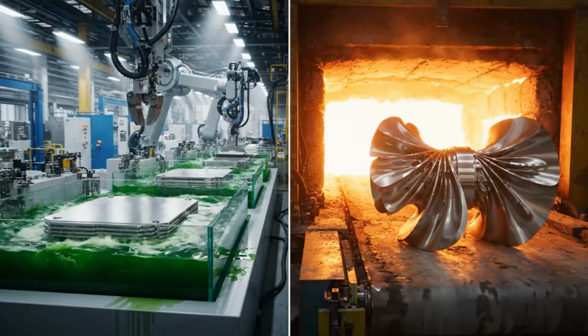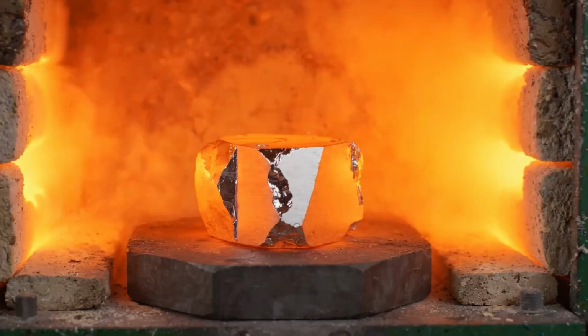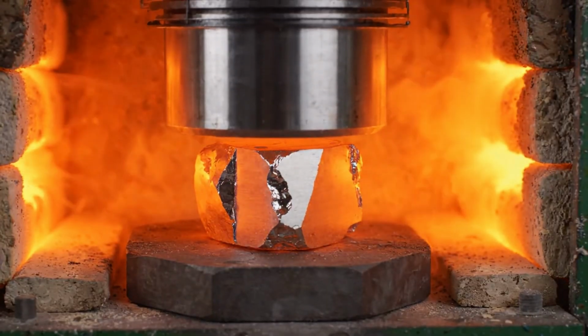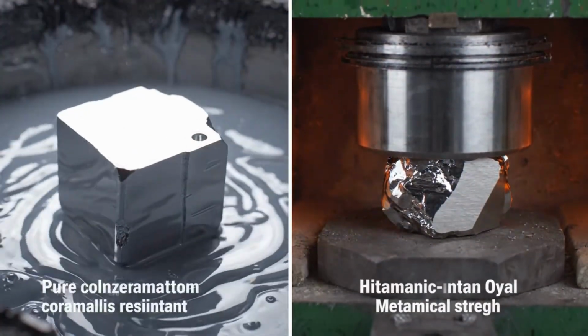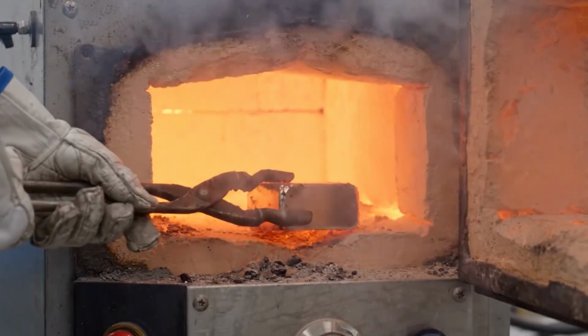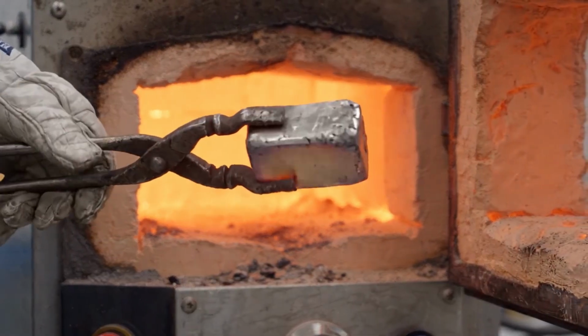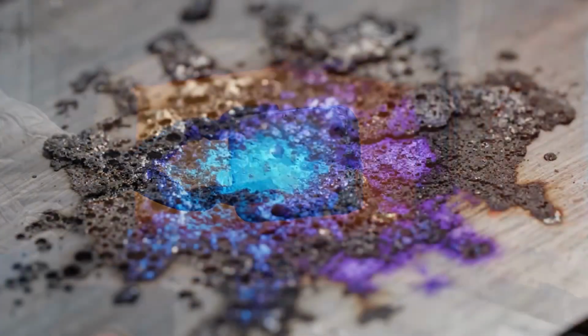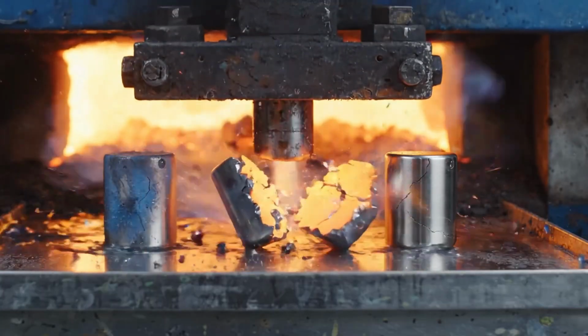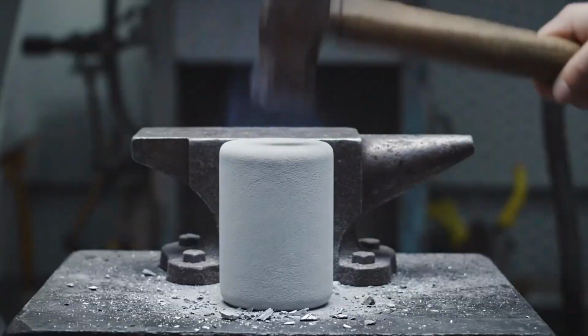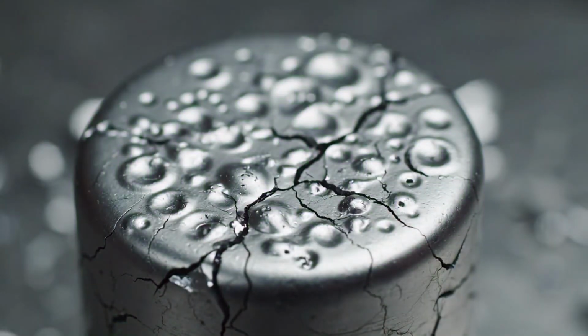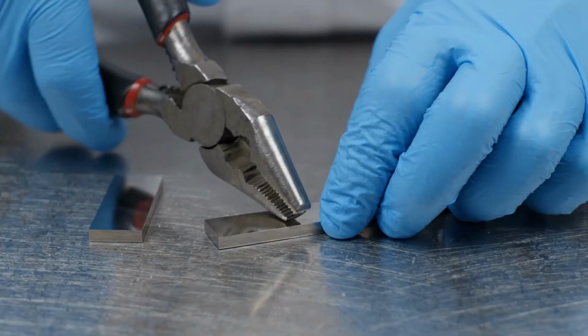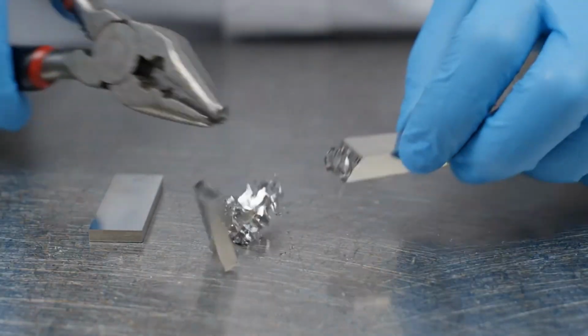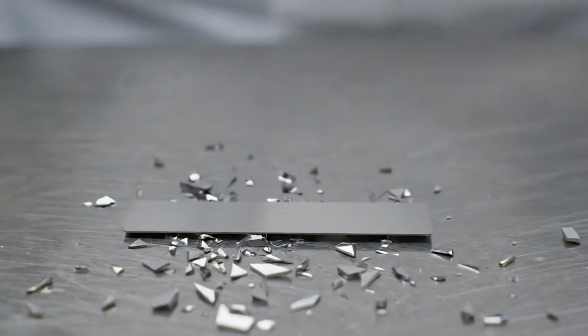This part of the process reveals another characteristic of titanium. It is strong, but delicate during manufacturing. At high temperatures, it readily absorbs gases. Oxygen can overharden it and reduce its ductility. Nitrogen can make it brittle. Hydrogen can cause internal problems. For this reason, operations are carried out under vacuum, argon, or controlled atmospheres. Industrial cleanliness is not a minor detail, but a prerequisite for the metal to retain its properties.